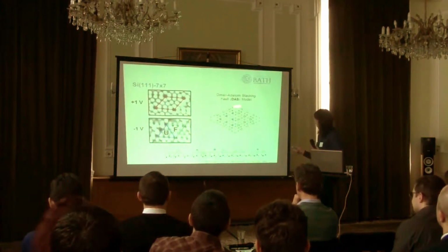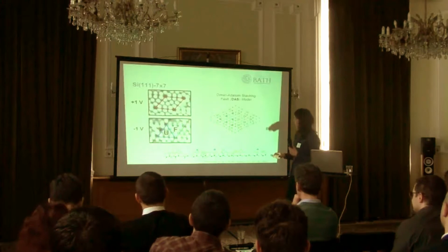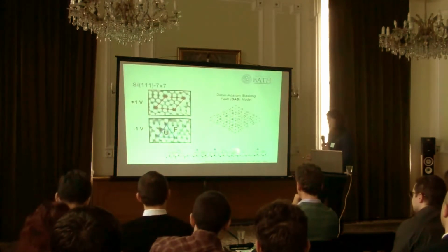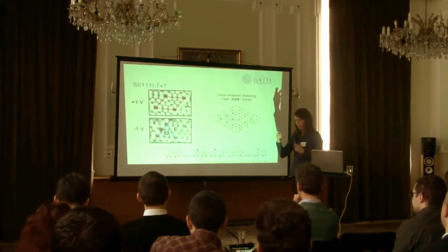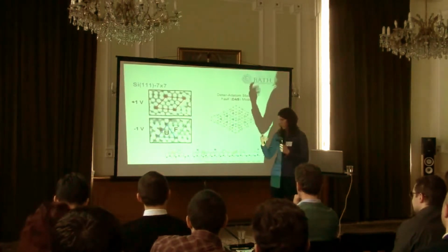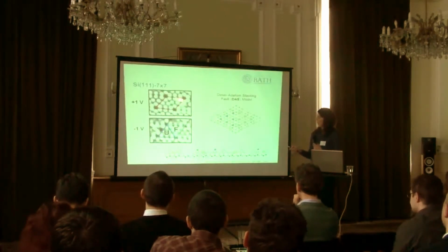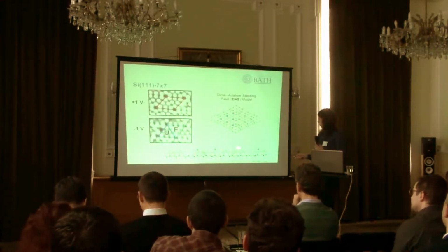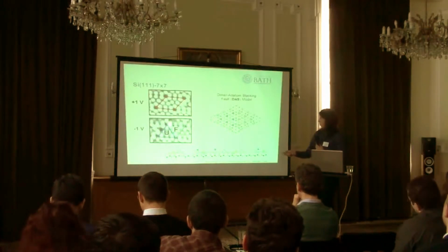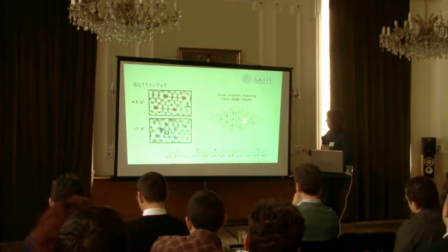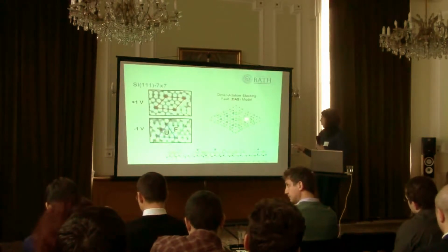So this is what the silicon surface reconstruction is actually like. It has 4 different layers to it. So the silicon surface actually comprises 4 layers, and what we see is just the adatoms on the top layer. So these ones here. And the reason why these ones look bright is because there's a stacking fault on this half, and that's the dark dots in between the adatoms.